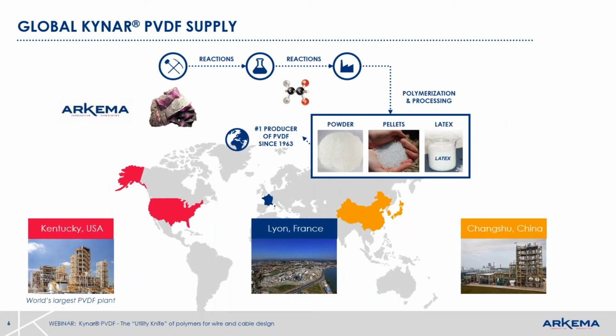From a global supply standpoint, in order to produce PVDF, you need to mine this rock. It's called fluorspar. It's a fluorine-containing mineral, and we take fluorspar and synthesize it through our emulsion polymerization method, and we generate a latex. We dry the latex to a powder. We densify the powder and extrude pellets. So most people in the cable world utilize pellets of PVDF in their extrusion of cable jackets.